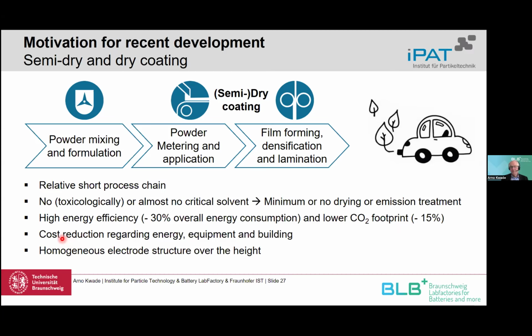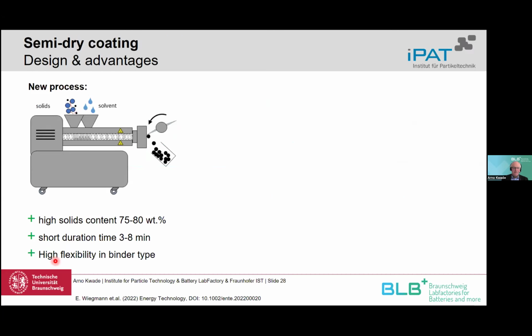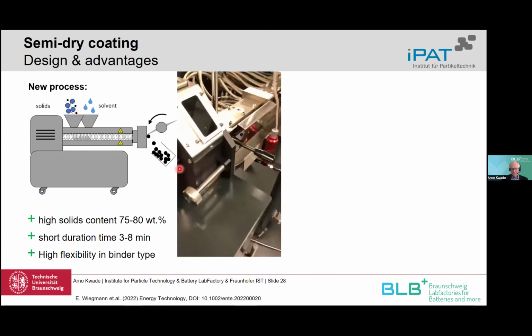At the moment, for a coating line, you need a building with a length of about 100 meters, so really big buildings. This can be much shortened, maybe to 10 meters, by the dry coating process. And we also have no migration anymore. To start with the semi-dry coating process, that is something we developed at our university and also patented. Here we produce by the extrusion process not a suspension. We really produce granules, which are soft and deformable.